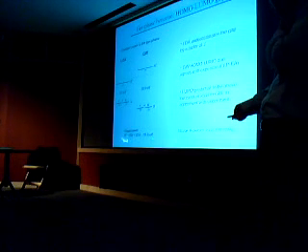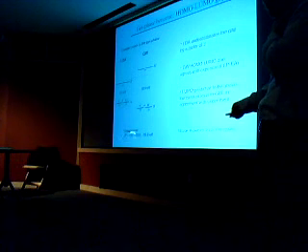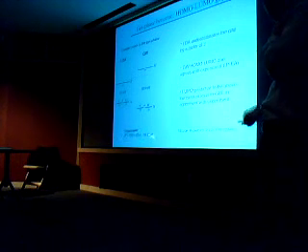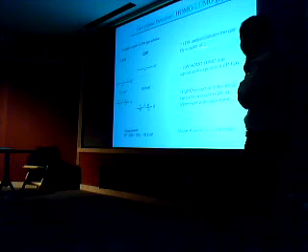Experimentally, this gap can be deduced by looking at the difference between the ionization potential and electron affinity, and gives you an experimental number somewhere between 10.4 and 10.6. So LDA underestimates the gap of the molecule by a factor of 2. The GW gap actually is in quite good agreement with the experiment. In fact, it also gives you a LUMO above the vacuum level.